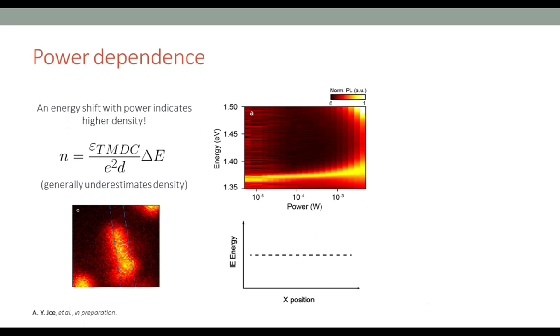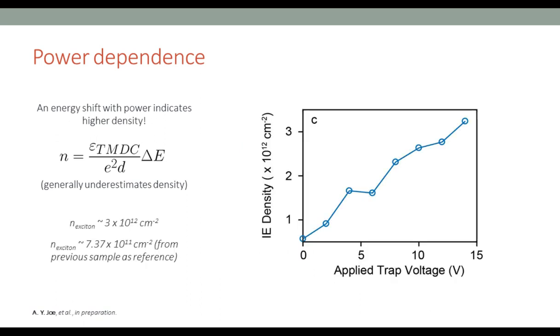So when the energy of the traps are flat, when we do a power dependence, it turns out that we see an energy shift of around 15 to 20 meV. But now, if you generate a trap and do the same power dependence, you can see that the energy at higher powers is almost limited by the depth of the trap. So the trap evidently is allowing a higher number of excitons to stay in the trap region, which makes sense. So from this, we can extract the density.